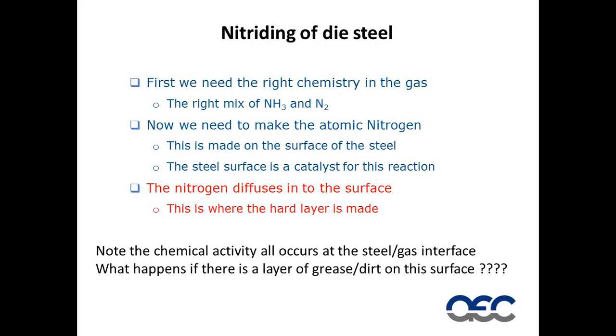Additionally, the amount of steel in there is important. So don't run your gas nitrider with just one die in it. You should run it at a full load every time. Now, what I used to do was I used to keep some spare dies which were worn out or had reached the end of their life, which we used to balance the load in the gas nitriding oven, so we had all the steel needed to cause these reactions to occur. Please, these may be scrap pieces of steel you're using, but they need to be just as clean as everything else which is in the reactor.